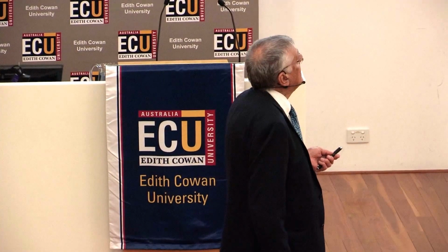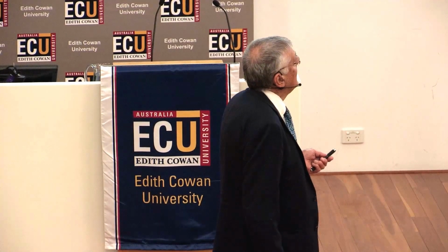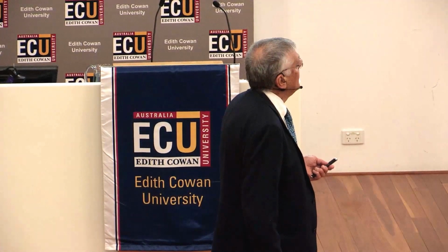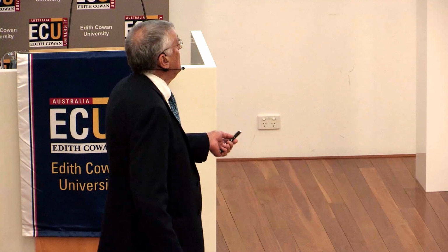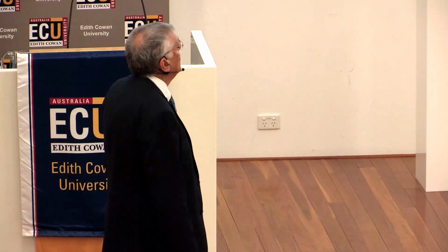And there are stable quasi-periodic materials based on the aluminum, lithium, copper system, and so on. So they are stable. Stable means that they melt congruently. Melting congruently means that you heat them up to the melting point and they do not transform on the way to anything else. This is congruent melting. So there are stable ones, metastable ones, and nobody ever discovered them before.